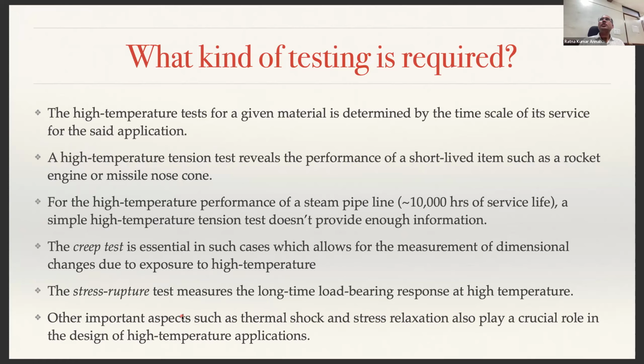Now, what kind of test do you need to do in order to see whether a material is good to be used under creep deformation or high temperature deformation? The type of high temperature test that you want to use for a given material is usually determined by the time scale of its service for the said application. For example, if you are designing a component for a rocket engine, we know for sure rocket engines are subjected to very high temperatures. Yes or no? Yes, sir. But then, do I need to design the component for creep? Just because it is subjected to very high temperature, do I need to design it for creep?